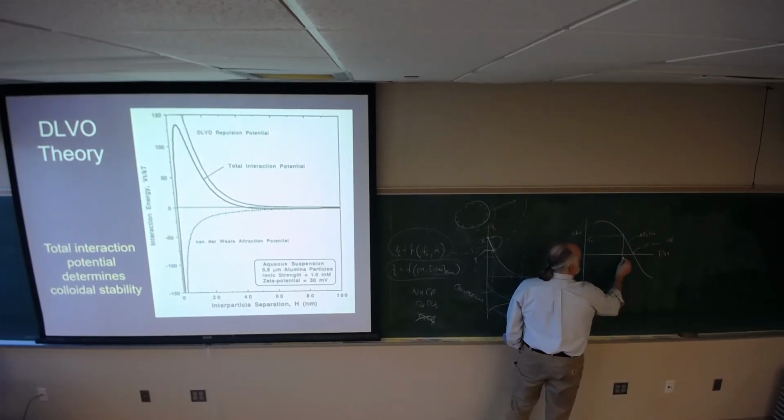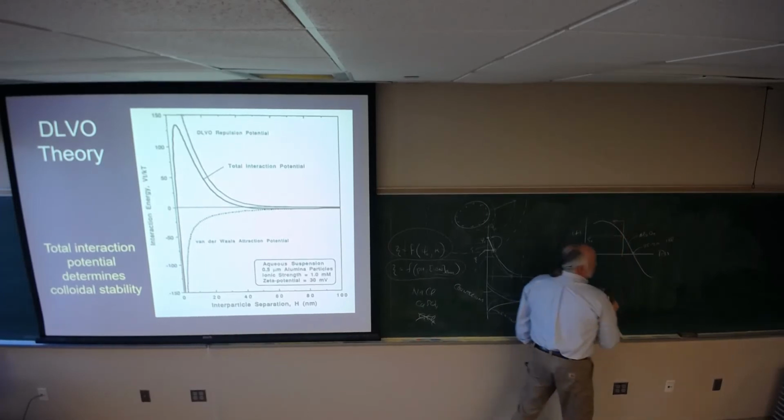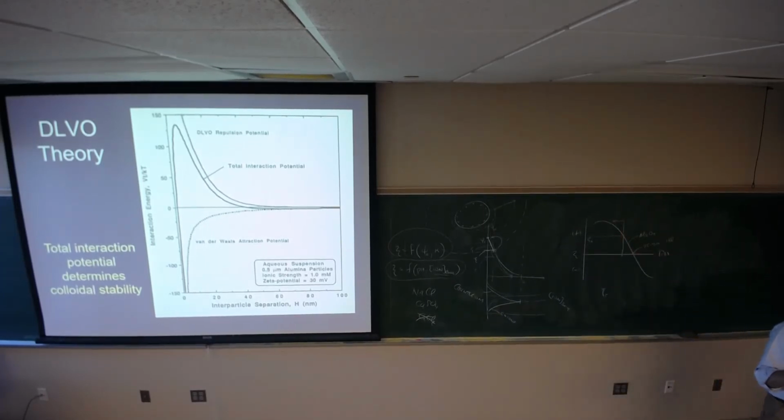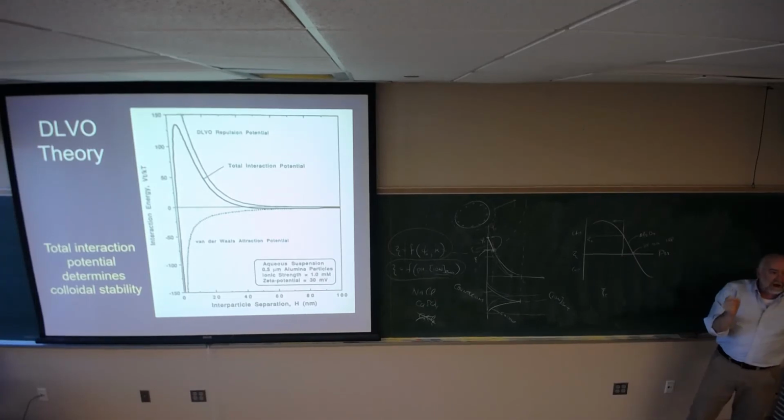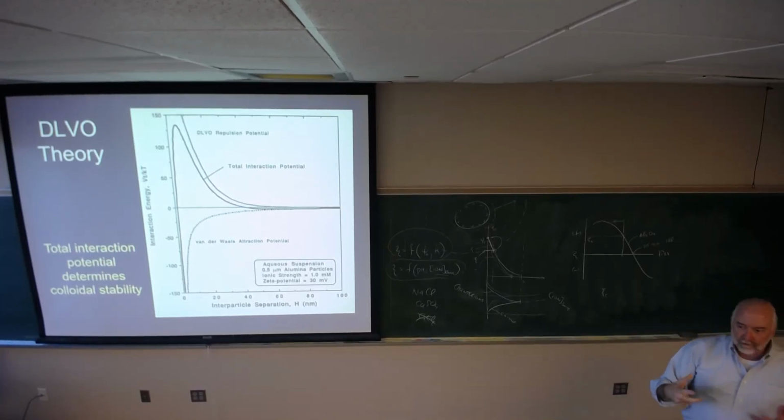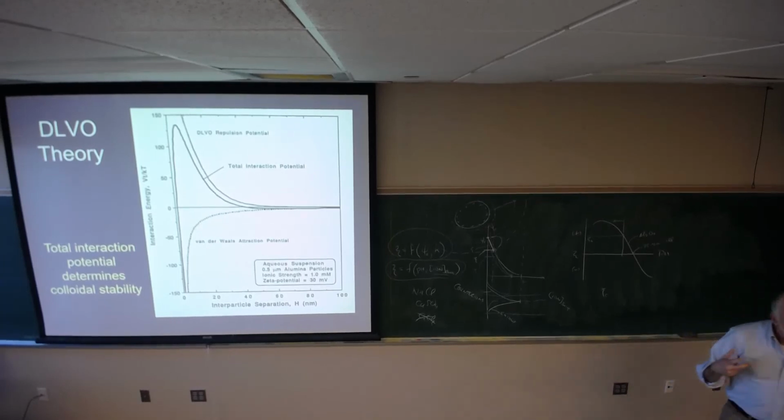and that means that I must be below a certain pH value for my suspensions to be dispersed. That's how you use this curve. I know that I have to get below some critical value of zeta potential, which we typically do not define. But you would know that as those particles get more strongly attracted to one another, that zeta potential value must get greater for those particles to repel each other. Or conversely, if particles are naturally not very strongly attracted, I don't have to have a very large pH or zeta potential in order for them to repel each other.